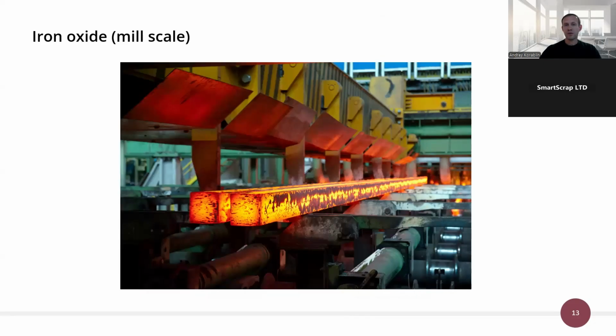On a deeper level, for metallurgists or those more familiar with the field, there is mill scale. This forms on the surface of a hot steel billet as it exits a continuous casting machine. As the billets cool, a flaky film develops on the surface known as mill scale, which is also iron oxide.